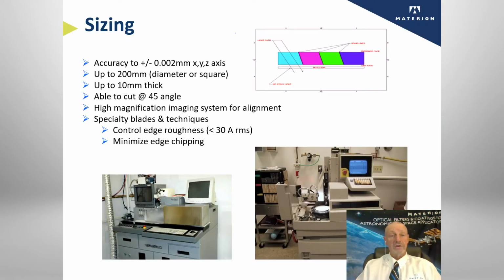So now that you have the coatings that you're looking for, you want to go into the sizing step. So we use specialty dicing equipment, which allows us to dice up to 200 millimeter wafers that are 10 millimeters thick. We can cut these wafers either straight cuts or angle cuts up to 45 degrees, which is what you would need if you wanted to build a parallelogram array and match the incident angle of the ray light coming in so that it would further reduce stray light and reflection.